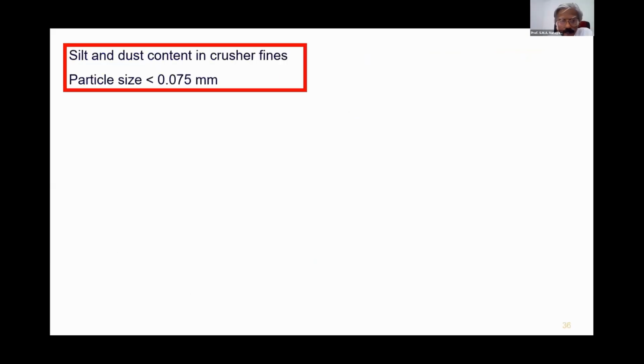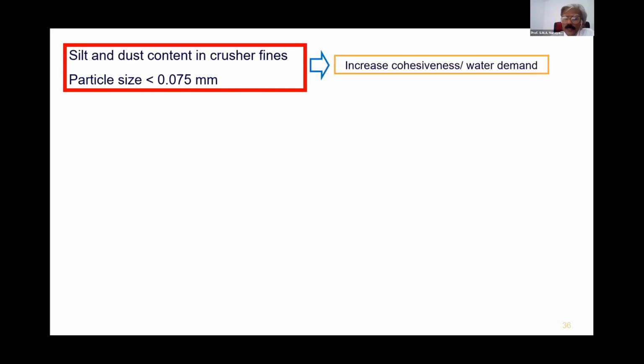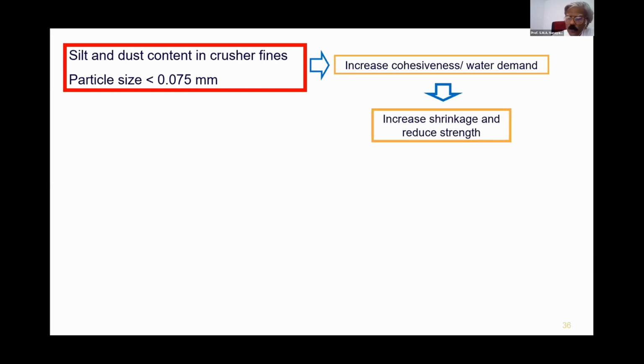Why do we have to process it? It contains very fine particles, particles less than 75 microns, and there are advantages as well as disadvantages of these fine particles. Because of this fine content, it will improve the cohesiveness of the concrete, that will prevent segregation. But the disadvantage is that it will increase the water demand. Now, if you don't use chemical admixtures, you have to increase the water content to improve the workability. Now, that can result in increased shrinkage and reduced strength.